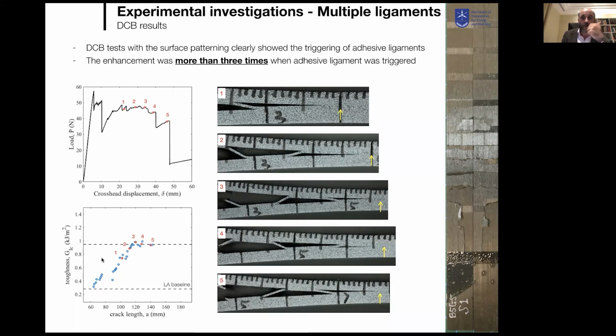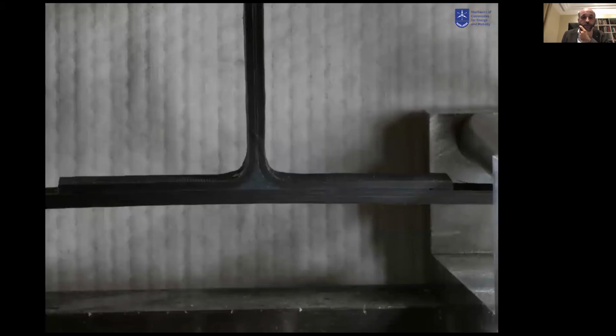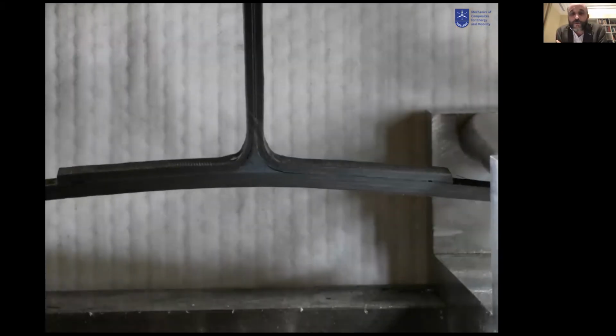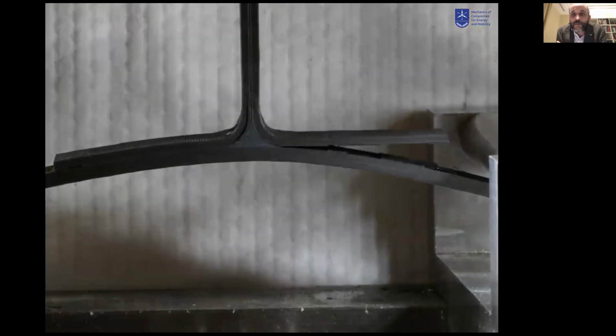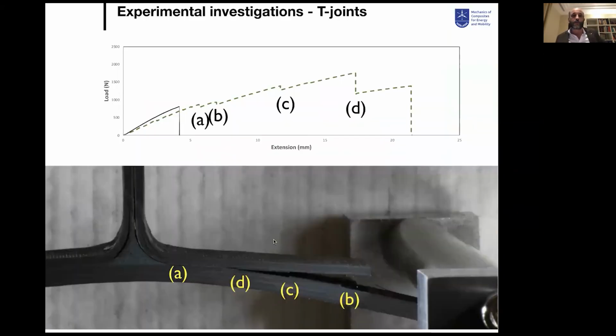So these are open paths on which we can work all together, and you see the effect of such technology when you go to real mini structures. So, for example, stiffeners for aeronautics. If you look at the failure or the delamination at stiffeners in aeronautics, you get an improvement using these technologies, the green curve, compared to the baseline black curve here. That is truly impressive. And each step of improvement here is clearly related to the progressive failure of the different ligaments that are introduced by the surface treatment.